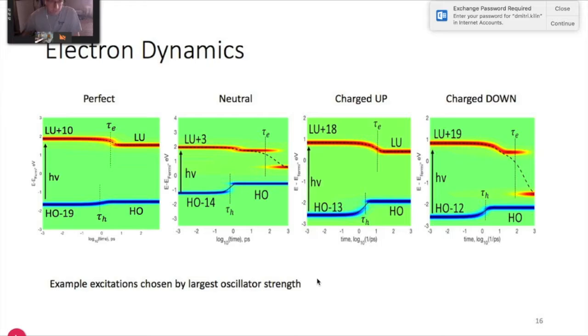And then moving towards the spin up and spin down, with the relative similarities between the charge up and perfect density of states, and also the charge down and neutral density of states, we would expect them to have similar rates and lifetimes of charge carriers, and indeed that is what we see, where the charge up has relatively small charge carrier lifetime, whereas for the charge down with this additional beta state, the lifetime is extended and there's a much more drastic change between the two charge carriers.